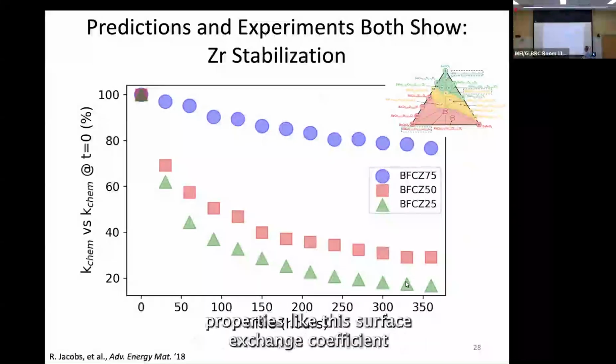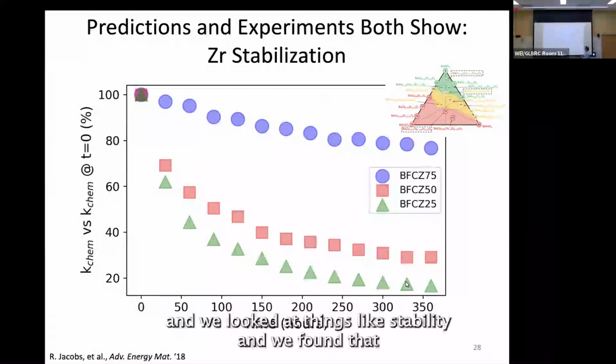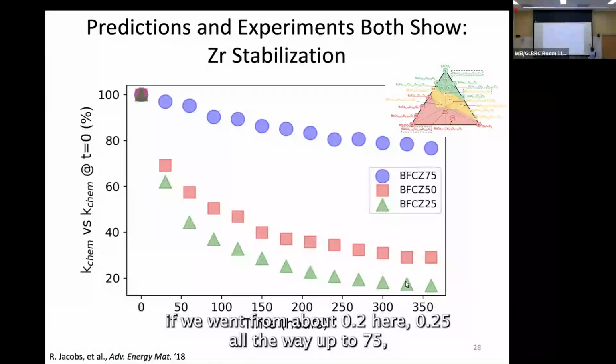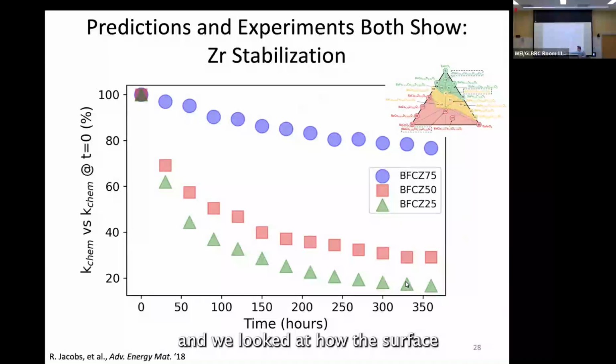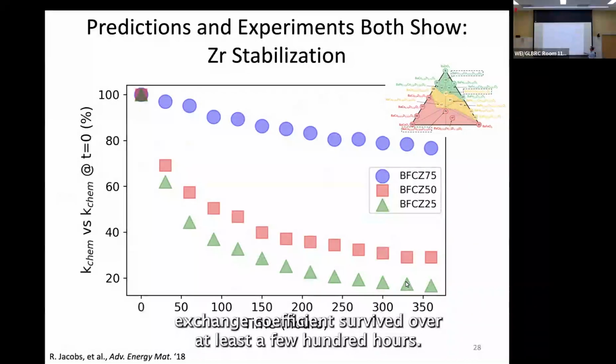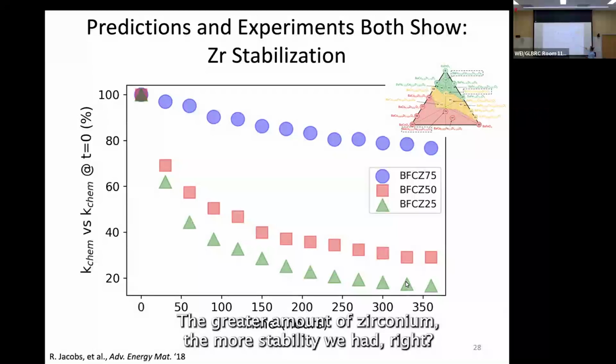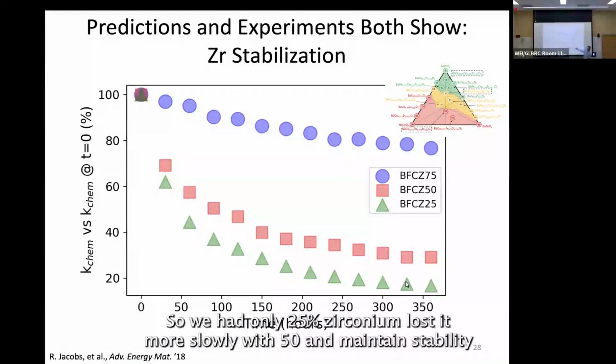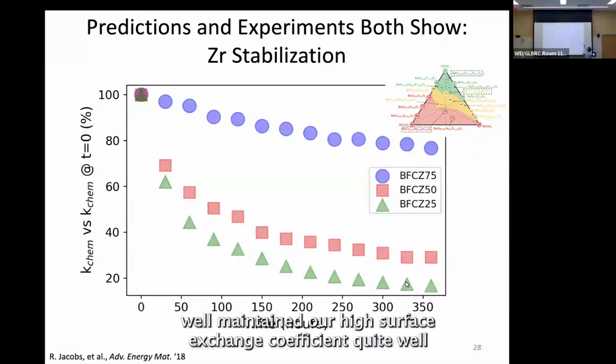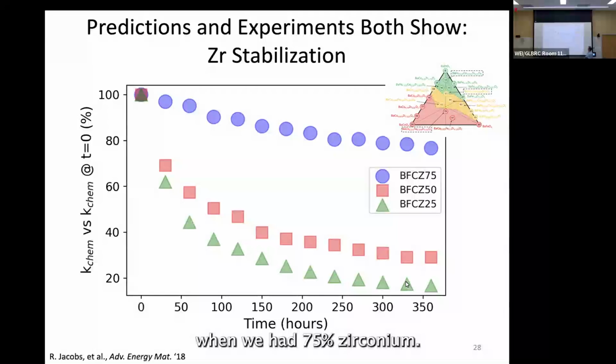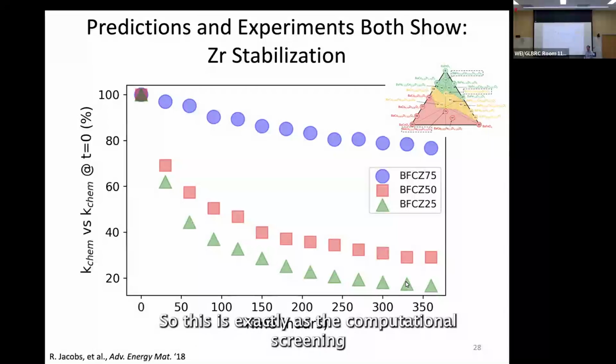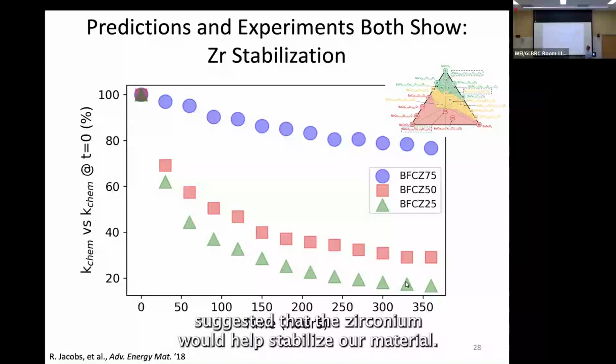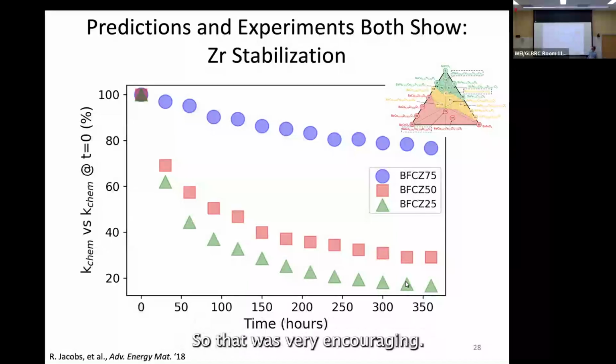And we looked at some of the properties, like this surface exchange coefficient. And we looked at things like stability. And we found that if we went from about 0.2, here 0.25, all the way up to 0.75, and we looked at how the surface exchange coefficient survived over at least a few hundred hours, the greater the amount of zirconium, the more stability we had, right? So we lost stability really fast when we had only 25% zirconium, lost it more slowly with 50, and maintained our high surface exchange coefficient quite well when we had 75% zirconium. So this is exactly as the computational screening suggested, that the zirconium would help stabilize our material. So that was very encouraging.